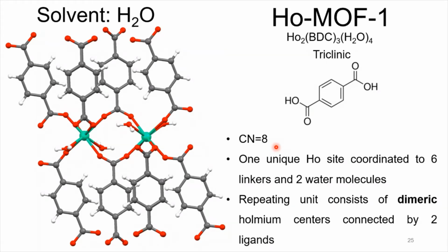So this coordination number will really open up the architecture that you end up with. In particular, here we can see that we have one unique Holmium crystallographic site. Each one of them will coordinate to water and the linker. But what is interesting, and this is what we call repeating units, so you'll take this unit to the left and just repeat it over and over and over in 3 dimensions, and that's how you visualize the final MOF